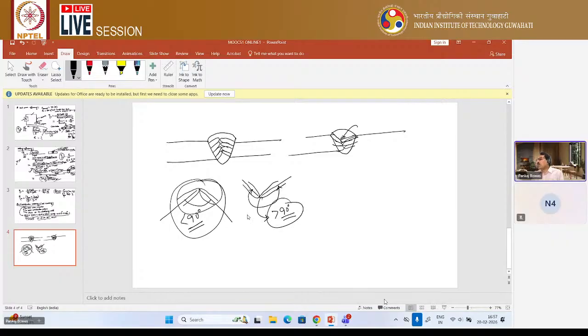And if it is the downward direction, then segregation of impurities of the weld material can accumulate here. That can create some compressive strain. Some strain phenomena can arise here, which promote solidification cracking. These are the things you should keep in mind. So solidification cracking depends on very important factors. One is UCS, which depends on weld metal composition, and you should keep the UCS value less than 25. The other is your grain orientation. If you can control these, that means UCS less than 25, then you can prevent solidification cracking.